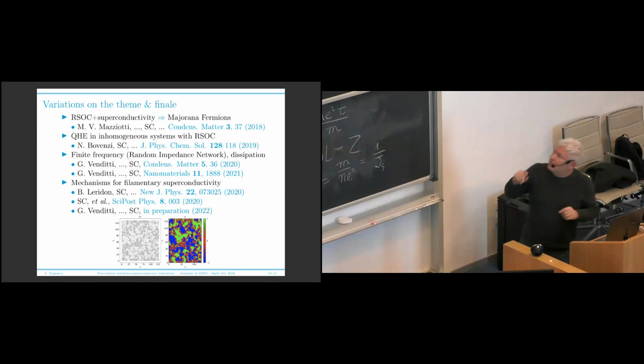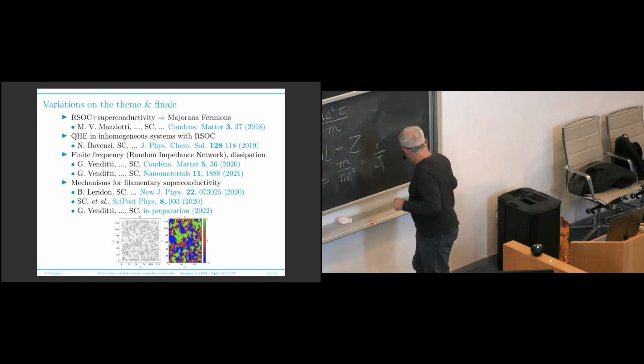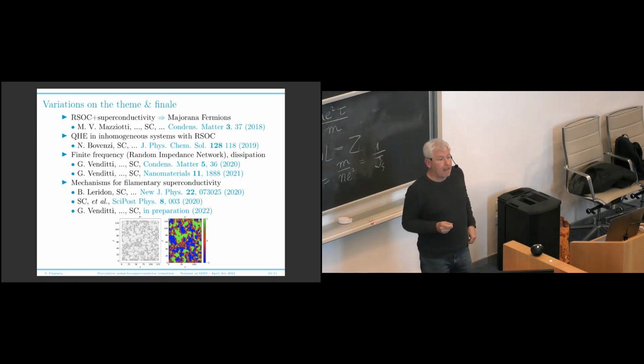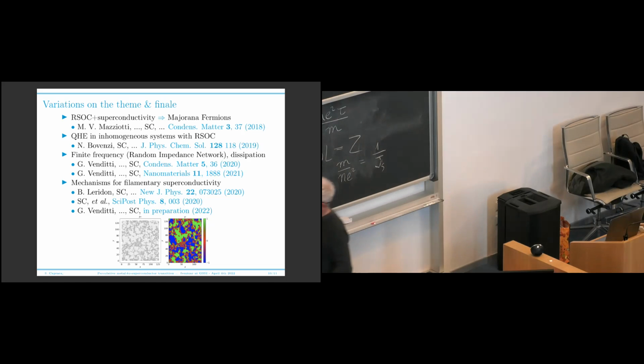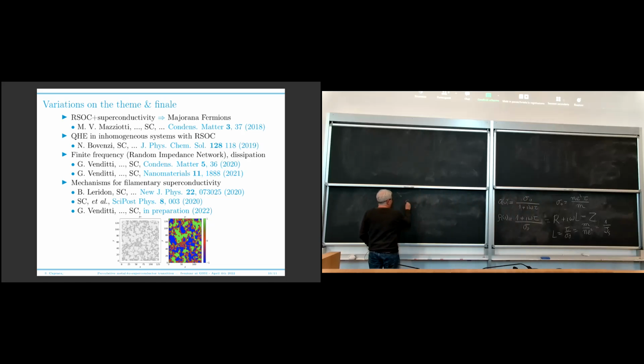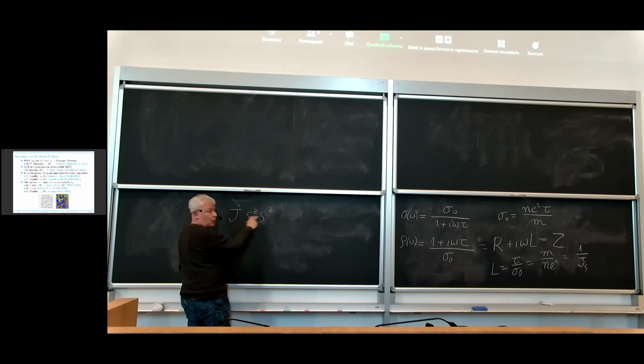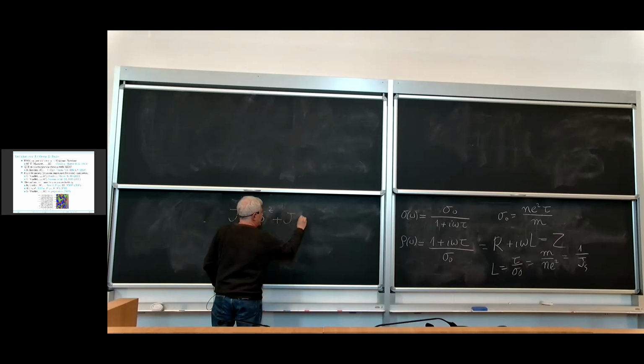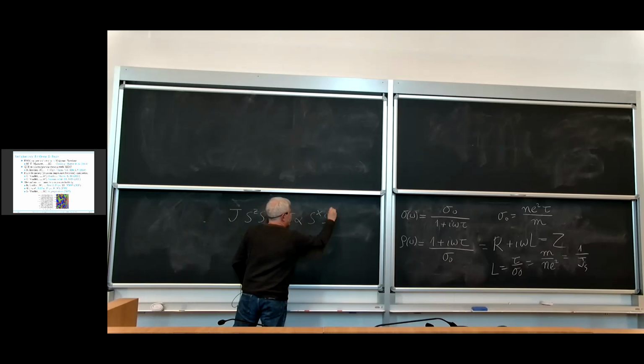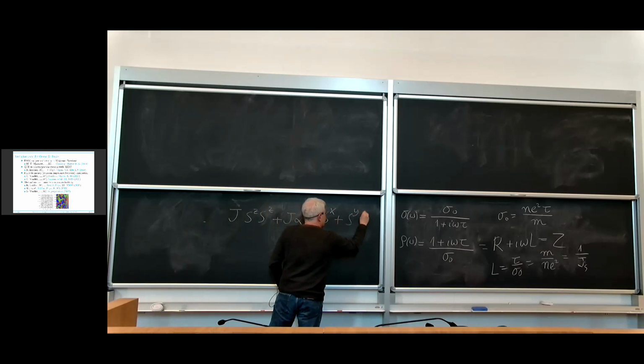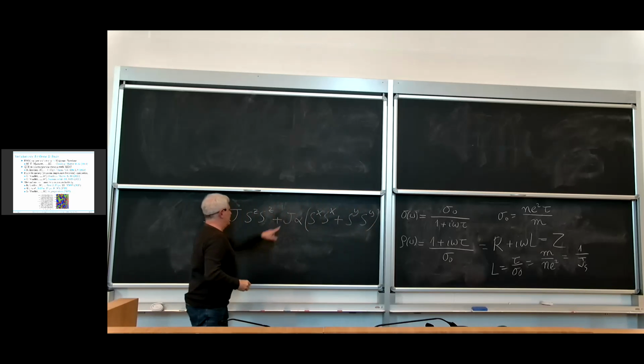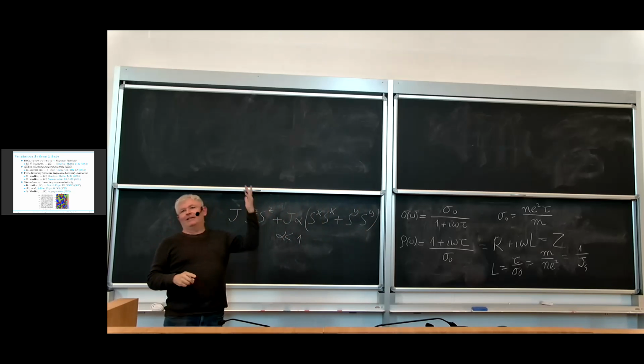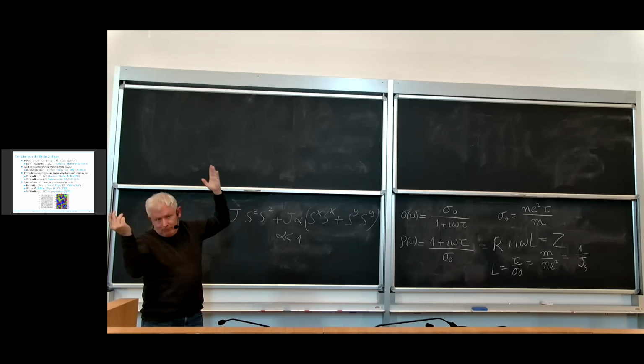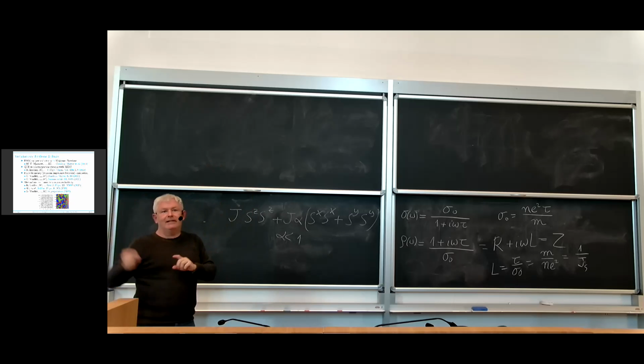So, this model is, imagine that you have some Heisenberg coupling of the spin, where you have a coupling J for SZ and then a coupling alpha J for X and Y. In the absence of disorder, if alpha is less than one, this model favors alignment along Z, up or down. This is degenerate, but you have a barrier in between.